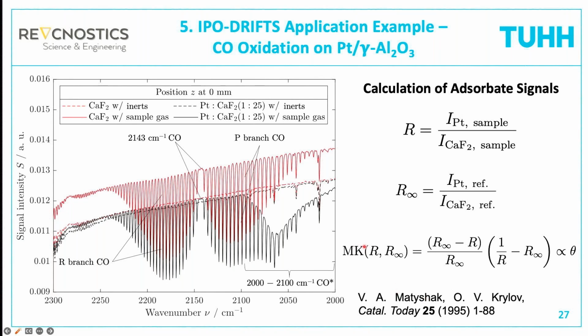And this is a modification of the Kubelka-Munk theory that takes into account that you have on the surface of your absorbers a thin layer of surface adsorbates. And this function is proportional to the coverage of the molecule. It's not a direct coverage, but it's proportional to it. So we can use this to judge how many molecules we have at the surface.